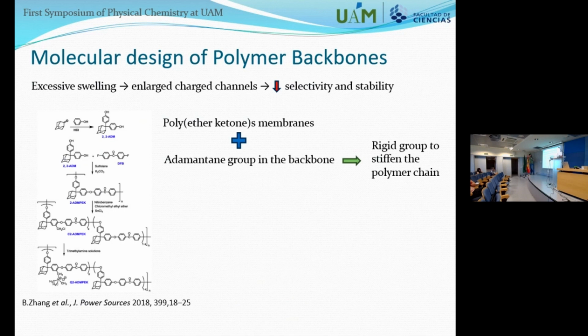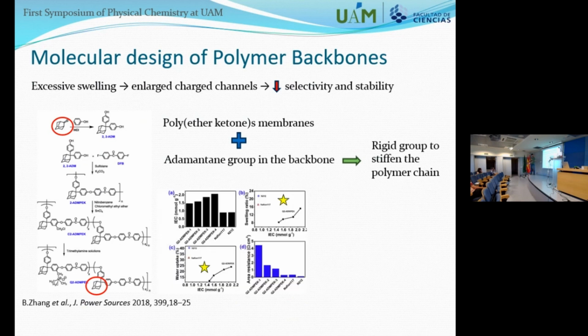So one of the ways that has been tried is to introduce groups in the backbone of the polymer chains. For example, in this work, they are using this adamantane group. They introduce it in the backbone because it's a very rigid group, and it helps to stiffen and make the overall polymeric structure more rigid. They find, well, sorry, this is small, but this is the swelling ratio. They obtain a small swelling ratio, so they are successful in that, and also a small water uptake, which is usually linked with the swelling ratio. So it looks like this is working to reduce the excessive swelling.